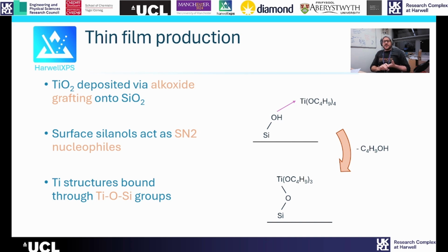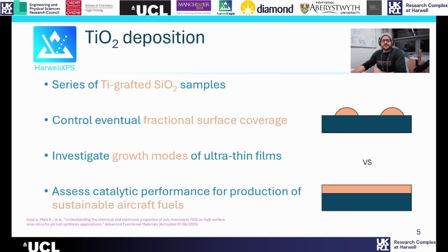And this is achieved using metal alkoxides in anhydrous conditions to prevent self-condensation and polymerization. And this uses the surface silanols as a nucleophile to add the titanium centers to the silica surface, liberating alcohol. What I wanted to do was look at how these monolayers deposit and condense, and determine what kind of different chemistries we can achieve with our eventual high surface area titanosilicates.